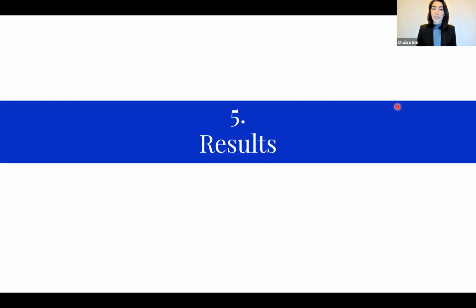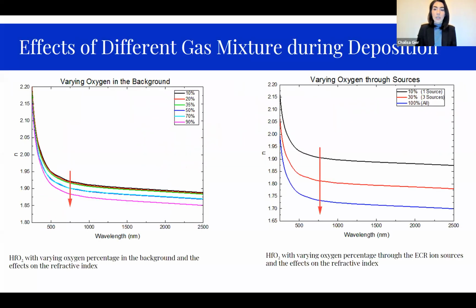And here are some results that I have accumulated during my PhD. So this is my most recent work, which is investigating the effects different gas mixtures have during deposition on optical parameters. We looked at different oxygen percentage in the background, which is shown in this graph here, and also looked at different percentage of oxygen as deposition gas. From this, we have found that as the oxygen percentage in the background increases, the refractive index of the film decreases. The same was also discovered for different oxygen percentage through the ion sources. I didn't show this here, but we also found that as the oxygen percentage increases, the bandgap energy also increases for both cases.